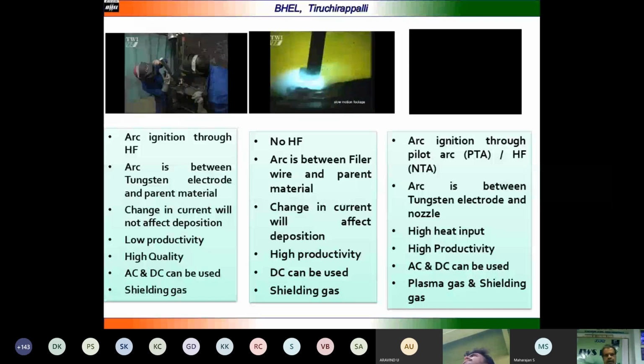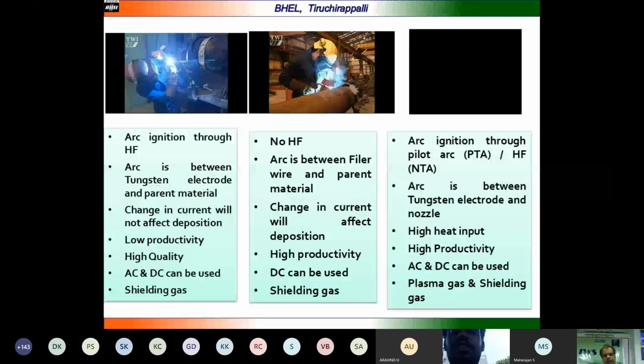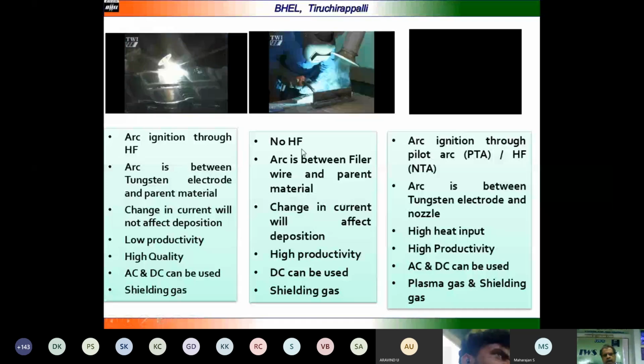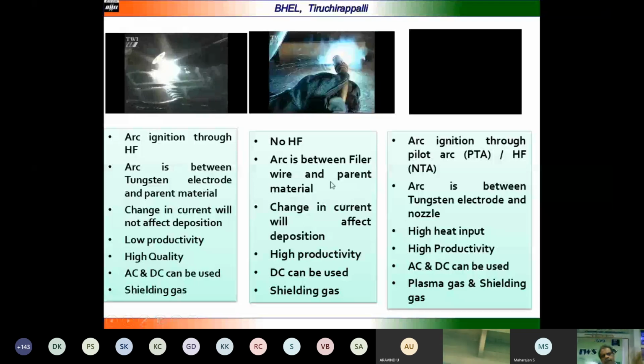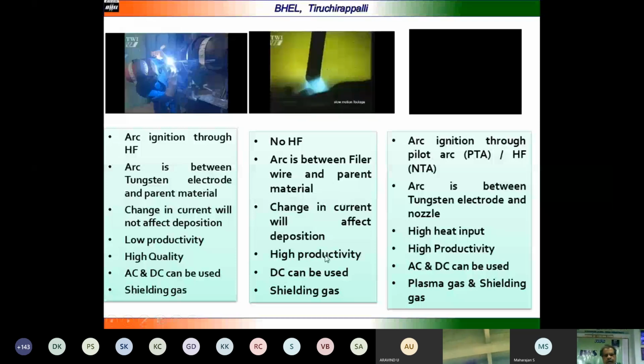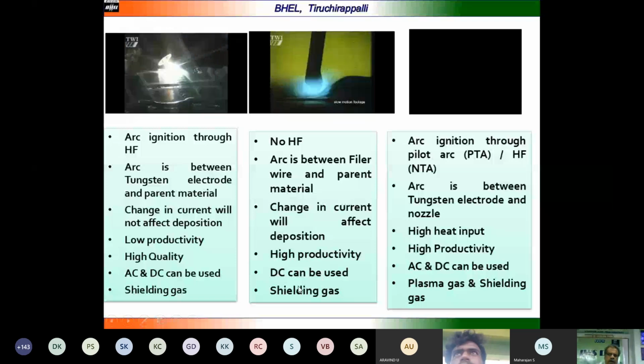Coming to the GMAW process, there is no high frequency unit. The arc is between the filler wire and the parent metal. Any change in the current will affect the melting rate, and the deposition is going to be affected. It's a very highly productive process, and DC, direct current, can be used, and the shielding gas can be argon, helium, or an argon CO2 mixture, or 100% CO2 here, depending upon the application.